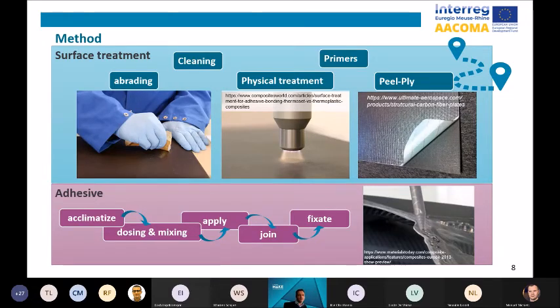By cleaning, thermoplastics are more sensitive to solvents compared to thermoset materials. The cleaning agent or the solvent can create stress cracks or dissolve the material. And so your cleaning agent has to be selected for this. And after cleaning, in most cases, you will need to activate the surface. I'll go through some examples.